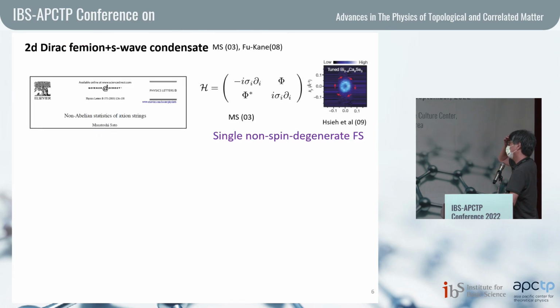For example, we can consider the two-dimensional Dirac fermion coupled with an s-wave condensate. The presence of the Majorana mode in this system was first mentioned in this paper in the context of high-energy physics. But later, in the context of condensed matter physics, Liang Fu and Charlie Kane considered the surface Dirac fermion of the topological insulators and the similar Hamiltonians. So anyway, I consider this Hamiltonian, a Dirac Hamiltonian, and this is the s-wave condensate. And as you know, if you consider the Dirac Hamiltonian, we have a single non-spin degenerate Fermi surface. So this means that once we create a vortex in the system, we can expect a Majorana zero mode.